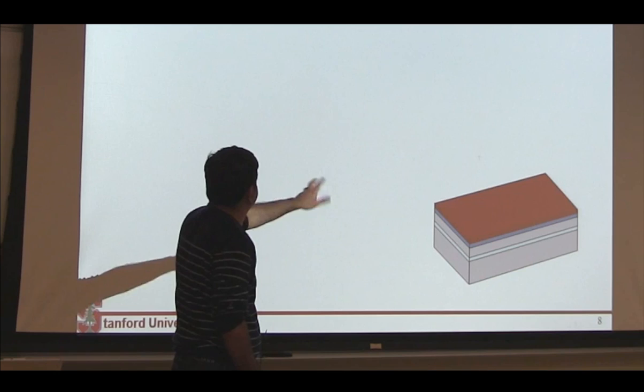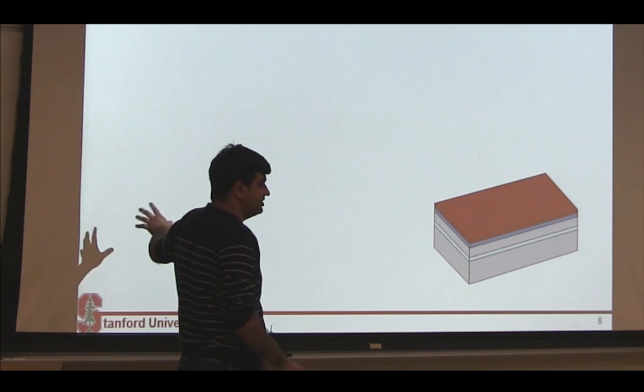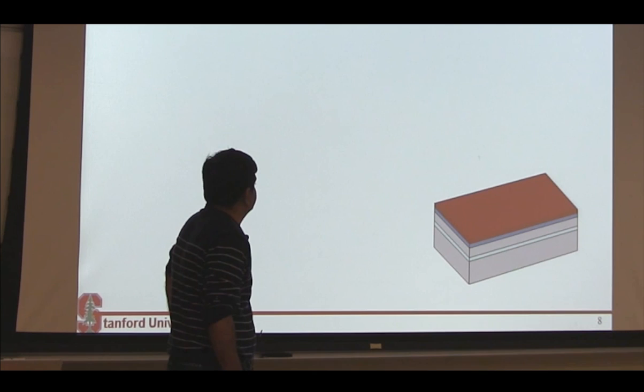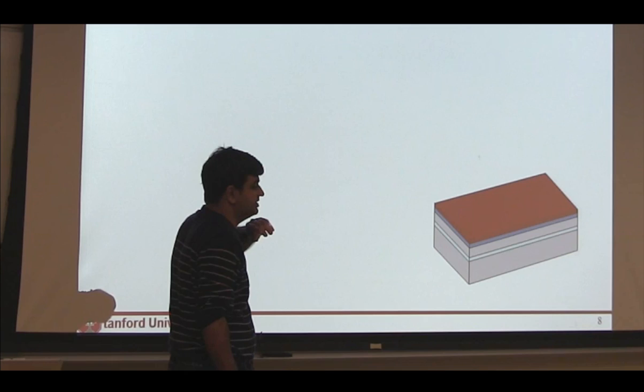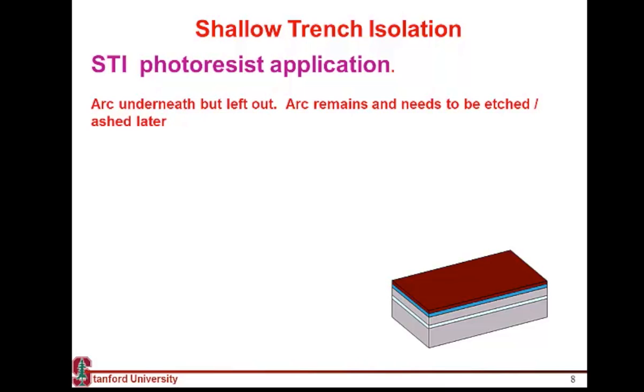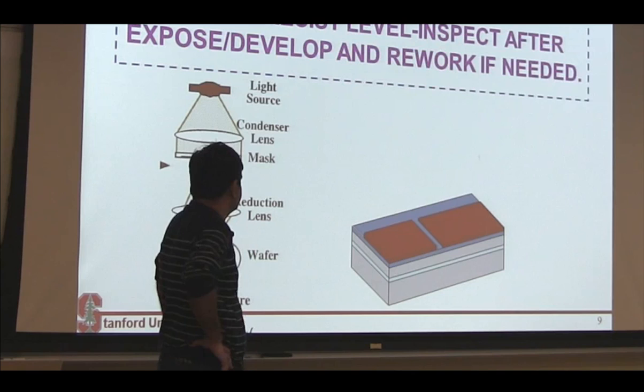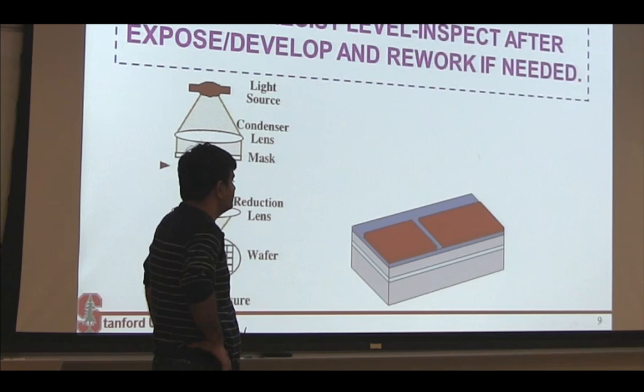Sometimes people use an oxide layer, not sometimes, almost all the times. People use an oxide layer below it because it helps in sticking. It also helps to reduce the stress. Another hard mask material we'll see later is titanium nitride, which is again a very difficult material to etch. So people use that as a hard mask. Then what you do is, once you have done your hard mask, you spin a photoresist. So you spin this layer of photoresist. I'm describing this process for once. We'll be repeating this again and again. So I want to make sure you understand the process of patterning and etching things the first time. So you spin a photoresist and these photoresists are these light-sensitive organic materials,